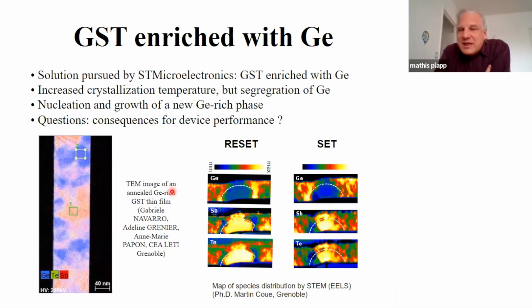They use the GST mixture, but not at the stoichiometric composition. They enrich it with germanium. So they move to the germanium-rich corner of the phase diagram. This indeed, according to their studies, increases the crystallization temperature. They can get it up to 300 degrees, which is quite good. But now when it crystallizes, it doesn't crystallize at constant composition.